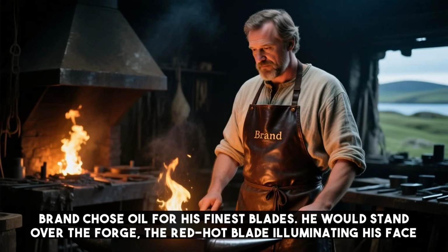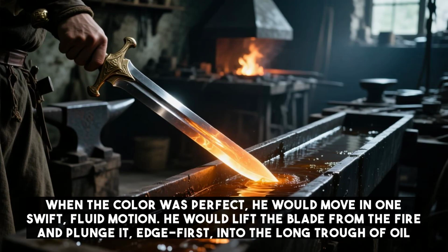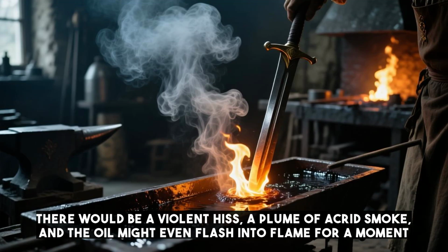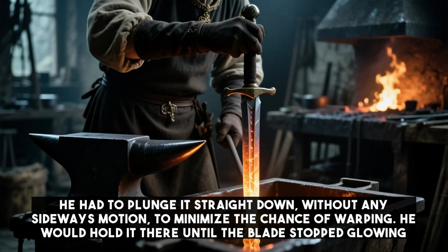He would stand over the forge, the red-hot blade illuminating his face. When the color was perfect, he would move in one swift, fluid motion. He would lift the blade from the fire and plunge it, edge first, into the long trough of oil. There would be a violent hiss, a plume of acrid smoke, and the oil might even flash into flame for a moment. He had to plunge it straight down without any sideways motion to minimize the chance of warping. He would hold it there until the blade stopped glowing.